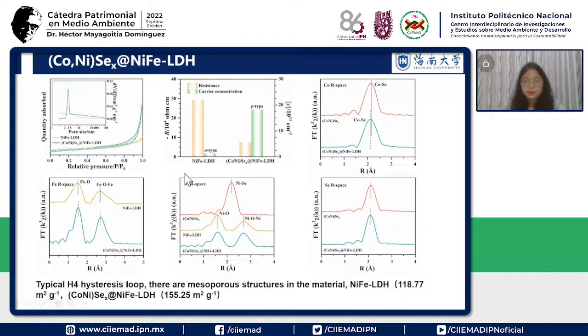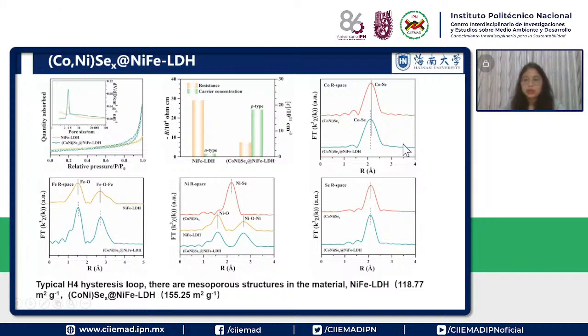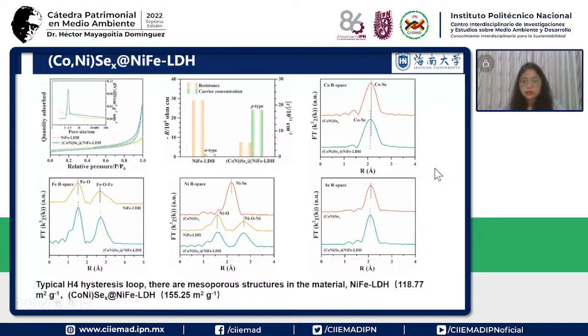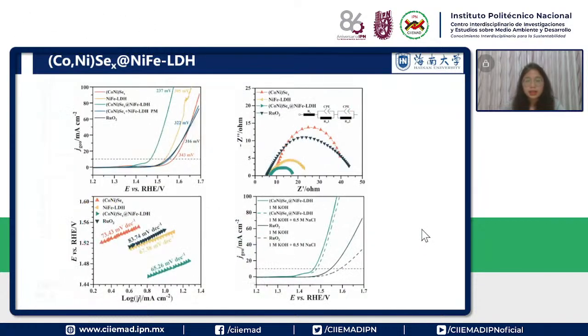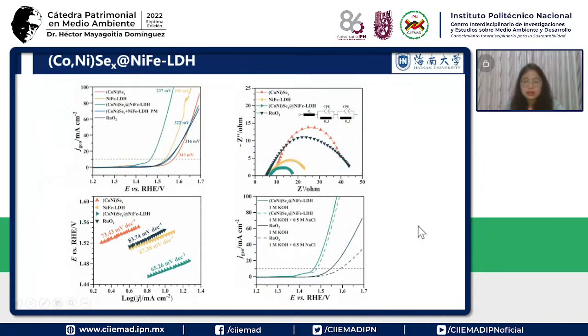And then we did hard synchrotron measurements to further confirm the species of the nickel selenide and the cobalt selenide here. And for the iron, it is iron oxide, which means it comes from the LDH. And then we tested the OER performance of these composites.